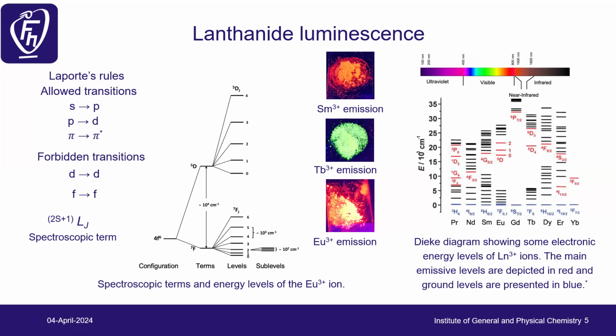Also, what is interesting, they emit in a very broad range of the electromagnetic spectrum, from ultraviolet, visible, and near-infrared up to the mid-infrared. Here, for example, we can see europium emitting in the visible, in red. Terbium emits in green, samarium in red-orange, and erbium emits in the near-infrared at the telecommunication optical window at 1.5 microns, as an example.